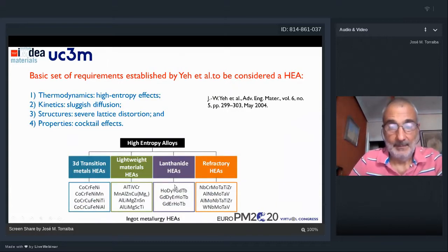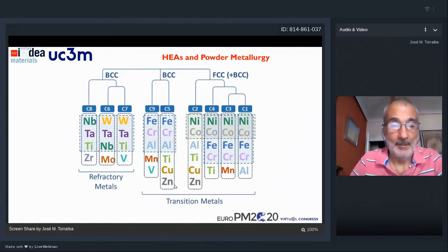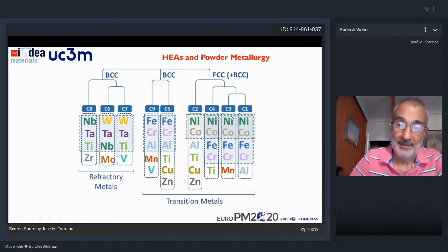But if we collect only the papers published on powder metallurgy and high entropy alloys, those 110, 120 papers, we can classify them mostly in 2 groups, refractory metals and transition metals. In the transition metals, we have this group in which we have in the middle the Cantor alloy with nickel, cobalt, iron, chromium, and manganese, and some other high entropy alloys in which we have replaced some of the elements of the Cantor alloy by other elements.